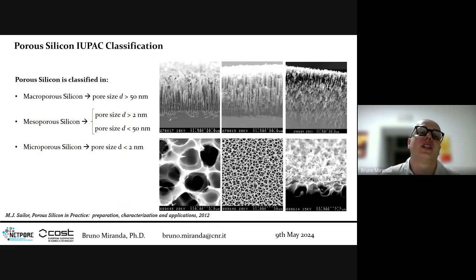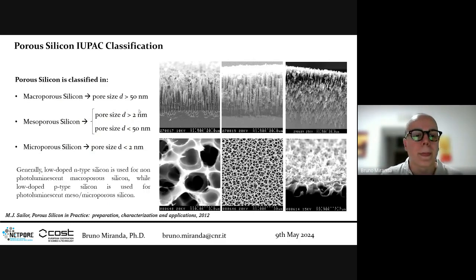IUPAC classification has been done for the classification of porous silicon. Basically, you have macroporous silicon if the pore size is higher than 50 nanometers, mesoporous silicon between 2 and 50 nanometers, and microporous silicon if it is lower than 2 nanometers. Generally, we use low-doped N-type silicon for non-photoluminescent macroporous silicon, while we use low-doped P-type silicon for photoluminescent mesoporous or microporous silicon.